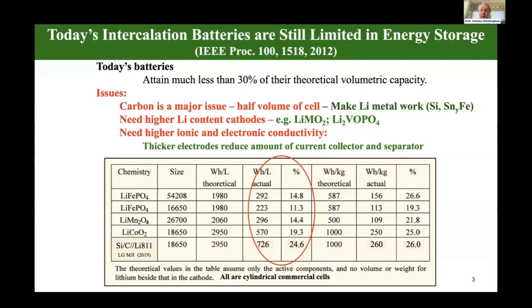To do this, we obviously have to get rid of the graphite in the batteries. The graphite takes up half the volume, and for every 7 grams of lithium, we need 70 grams of graphite. So we have to go away from the graphite anode. We also need higher lithium content cathodes. So it means we have to go to a higher lithium content in the layered oxides, and I'll show you in a moment, this means basically going to higher nickel. Or we can use the phosphates, but there we need to put extra lithium in. But for all these, ideally, what we want are materials that have higher ionic and electronic conductivities. This will allow us to make thicker electrodes, which will reduce the amount of the current collector and separator.